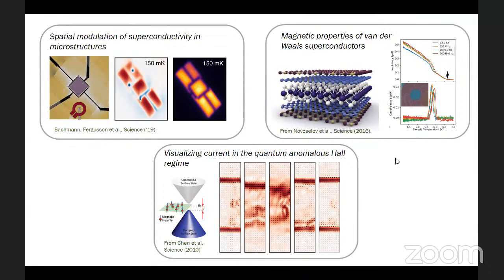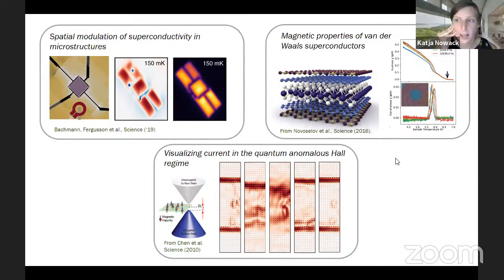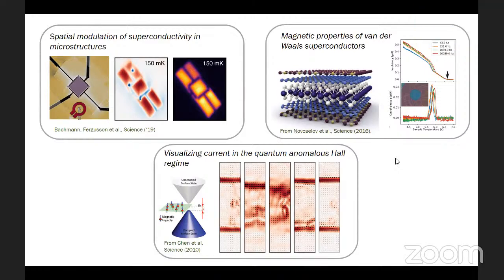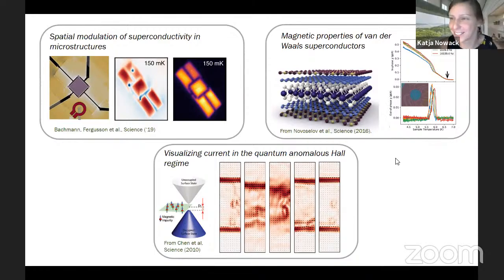And so we actually do have some squids with that size of pickup loops, 300 to 400 nanometer diameter. We end up not using them much because the signal also goes down with the area. So we are dialing in on these micron scale ones. With our squids, I'm saying you could maybe get to 0.5 micron, but not better.